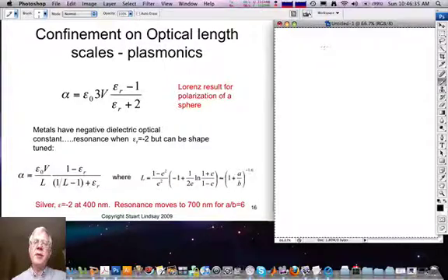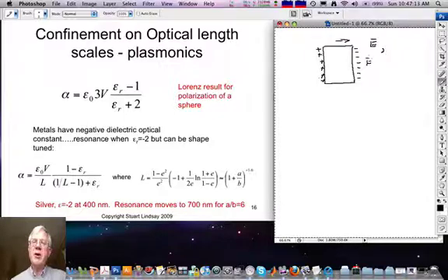In problem 7.4 at the back of chapter 7, which I urge you to do now if you have not done it before, we ask you to consider what happens when a small metal particle polarizes spontaneously as a result of a fluctuation of the electron cloud in this direction. So here are excess electrons, here an excess nuclear charge. We use Gauss's law to relate the electric field at the surface to the net charge on the surface.